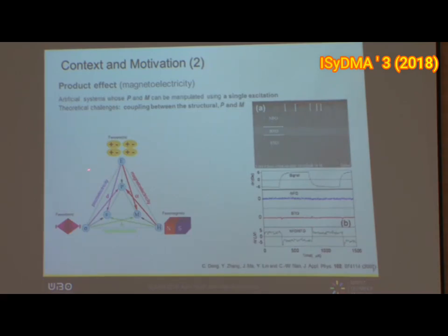The most effective way to realize the coupling between the two order parameters is to use mechanical constraints. This is called extrinsic magnetoelectricity, and the experimental realization is represented by results done using thin film geometry.